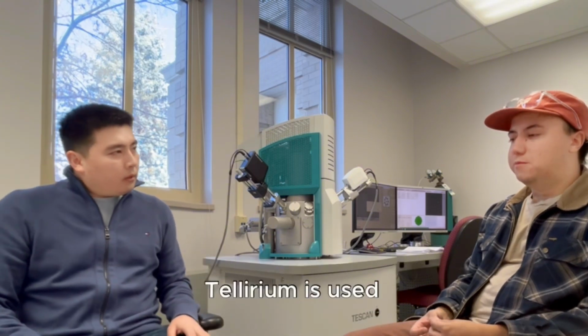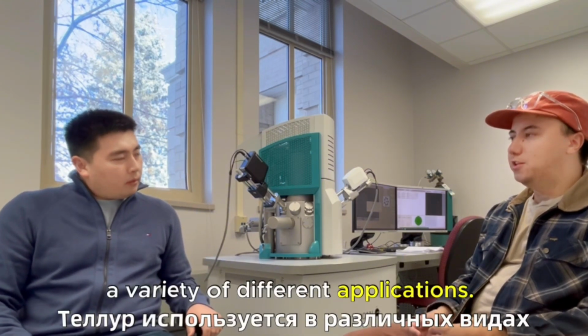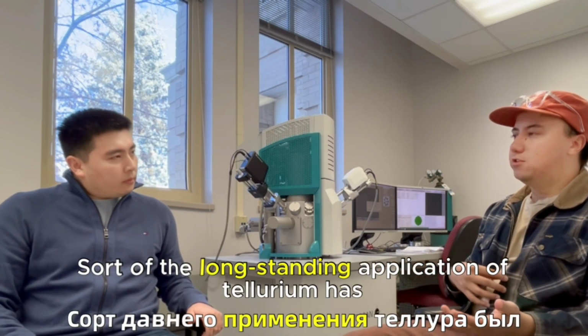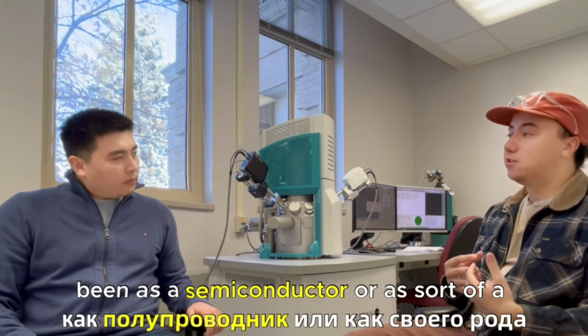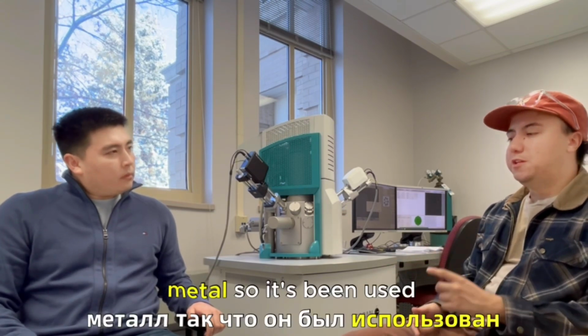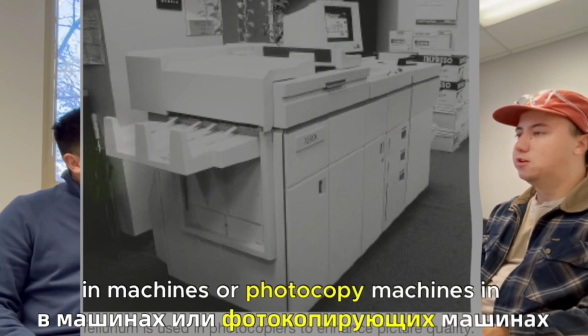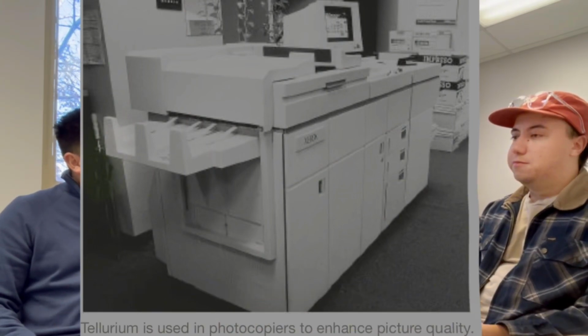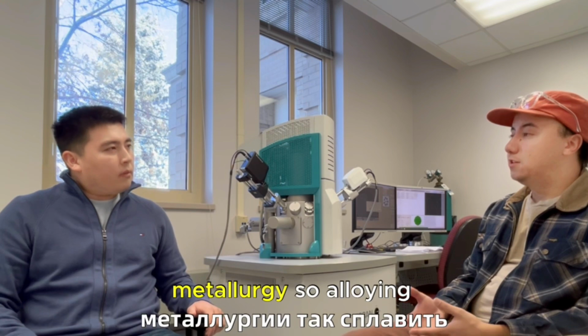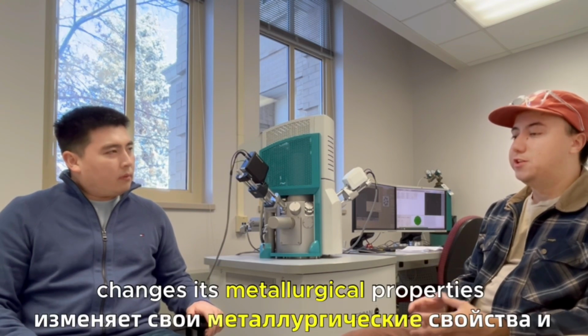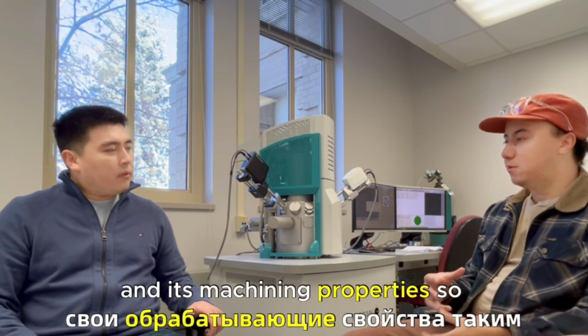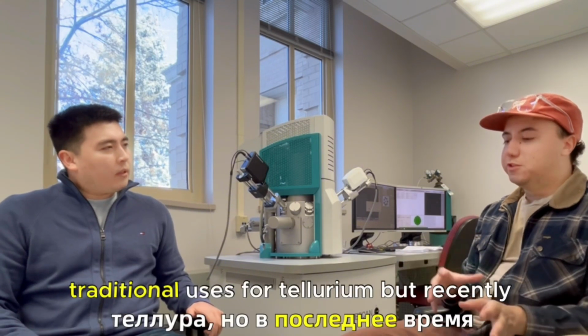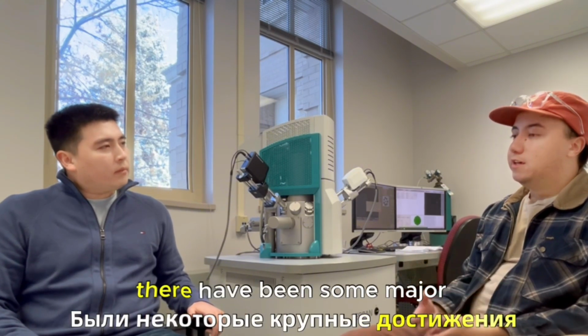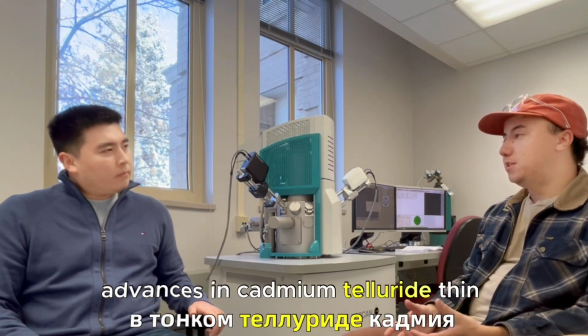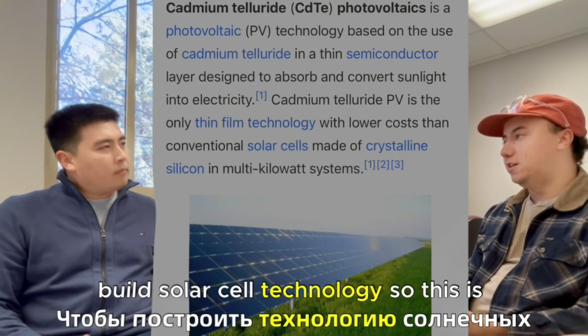Yeah. So tellurium is used in a variety of different applications. The long-standing application of tellurium has been as a semiconductor or as a technology metal. So it's been used in Xerox machines or photocopy machines, and in metallurgy. Alloying copper with tellurium changes its metallurgical properties and its machining properties. Those are the more traditional uses for tellurium, but recently there have been some major advances in cadmium telluride thin film solar cell technology.